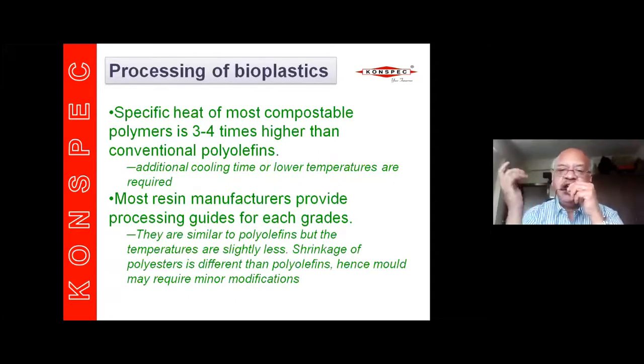Now, specific heat of most compostable polymers is 3 to 4 times higher than that of conventional polyolefins. So it won't cool very fast, and hence either additional cooling time has to be given, or the temperature of the coolants has to be reduced significantly to ensure that material is cooled properly before it is ejected out of either injection molding mold or thermoforming mold. Or even when we are making pipes or any other product like straws, we have to ensure that longer lengths are provided for cooling, or we have to reduce the temperature of the coolant, water bath or whatever way we are cooling it.